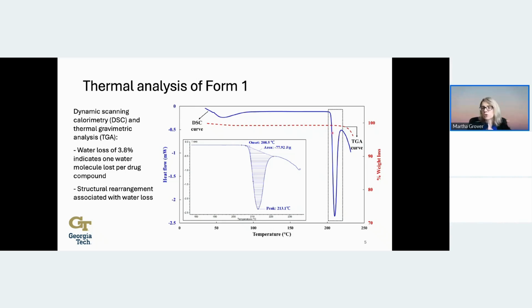And then there's a major feature which we associate with melting of the dehydrated crystal. There's not really weight loss occurring, although we attribute to decomposition the continued weight loss above the melting temperature. The inset here is just zooming in on this peak, but we were able to quantitate the DSC peak to come up with an estimate of the heat of fusion. We actually use that later in thermodynamic modeling, and I'll talk about that later, although if you're particularly interested in the thermodynamic modeling, you might like to read the paper, which provides more detail on those aspects.